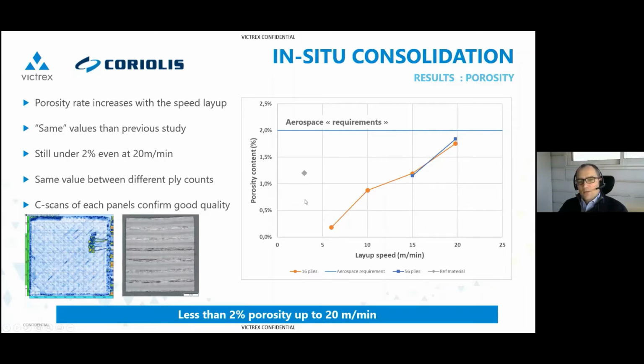Again, starting from the state of the art, the reference material, we were at potentially 1.2% for a speed of 3 meters per minute. So we are more or less within the same range, again, with the speed increased 5 times. That again goes in the direction of saying you can go faster and have the same quality of results. And we did some C-scan for each panel, and the quality of the laminate was pretty good.